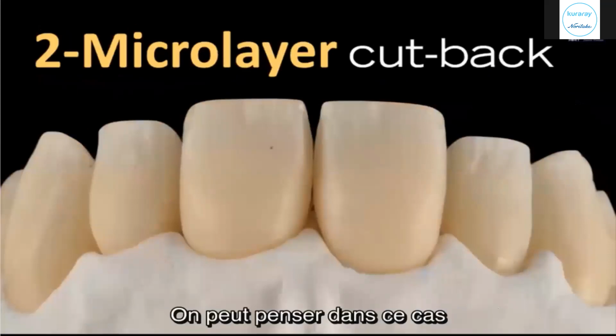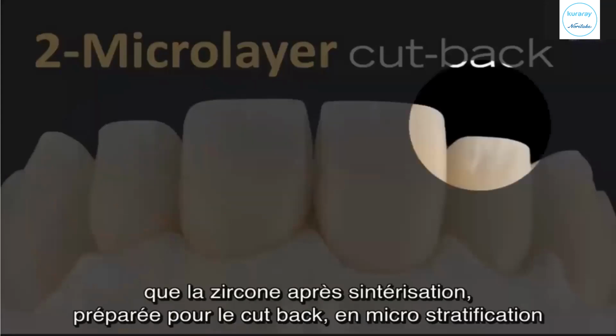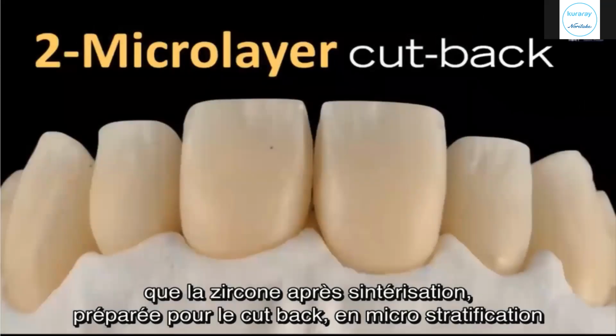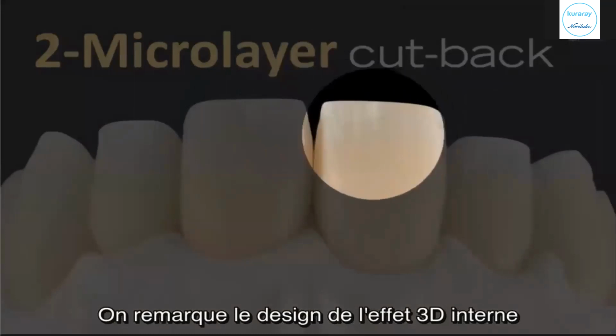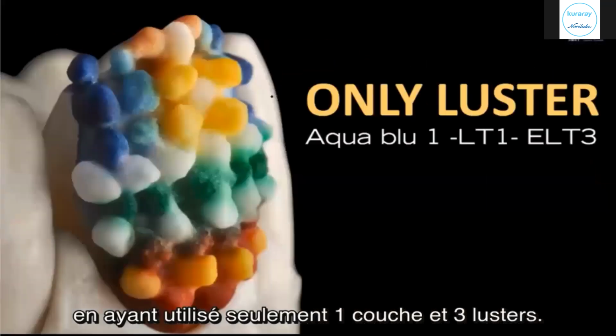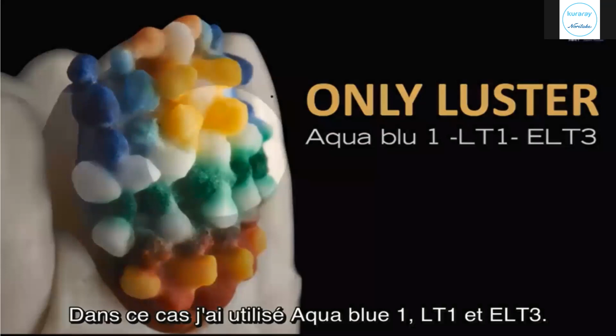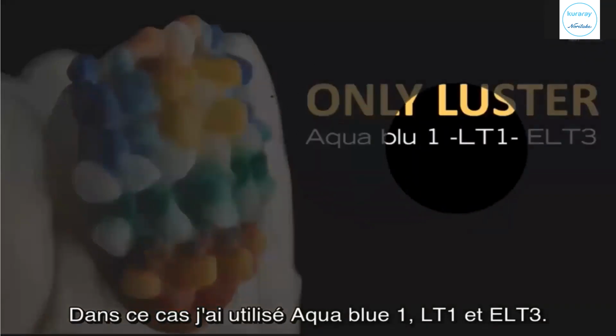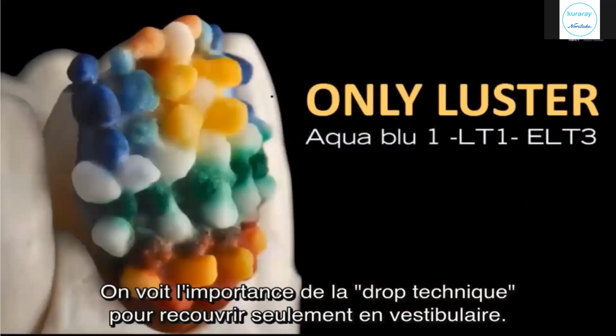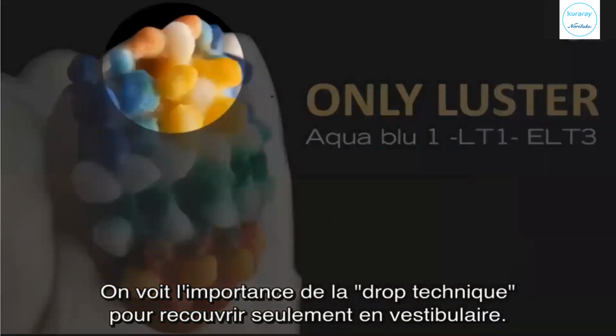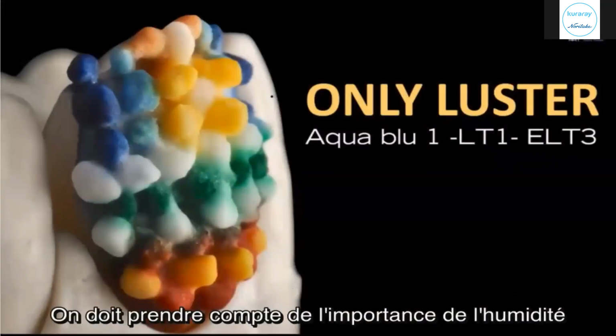We can see in that case the zirconia just sintered, prepared for the micro layer cutback. We can notice the internal design is a 3D internal design, using only one layer and only 3 lustre. In that case, I use aqua blue 1, LT1, ELT3, and we can see an important step, the drop technique to cover only the vestibular. We have to consider the importance of the humidity.